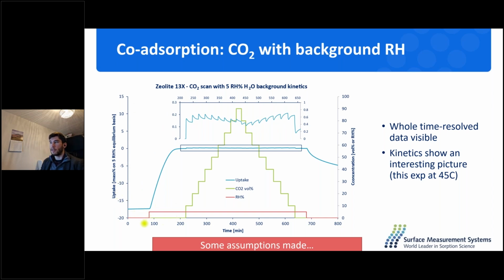This is the entire kinetics of the previous experiment. We have in red the concentration of water. This is the pre-saturation with water at 5% relative humidity. The whole experiment is being kept at 5% relative humidity, and then CO2 is being dosed on top from 0 to 90%. If we zoom in to when CO2 is introduced, we see that there is definitely an uptake, but then there is a slow equilibration step where something is happening.